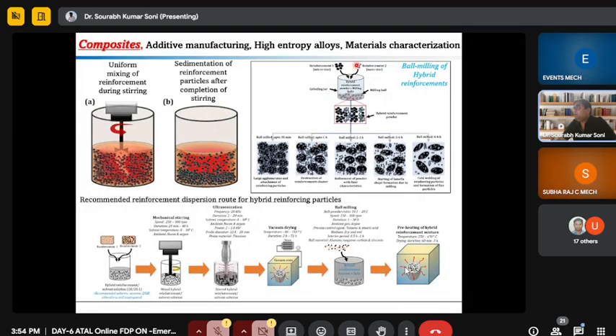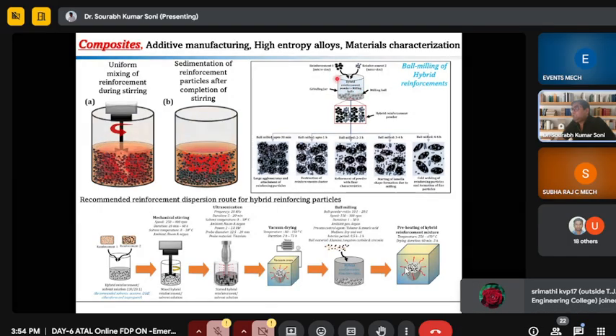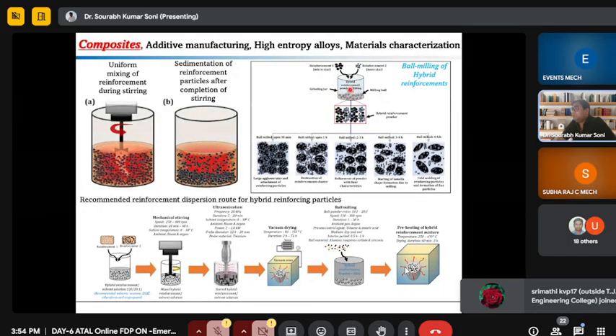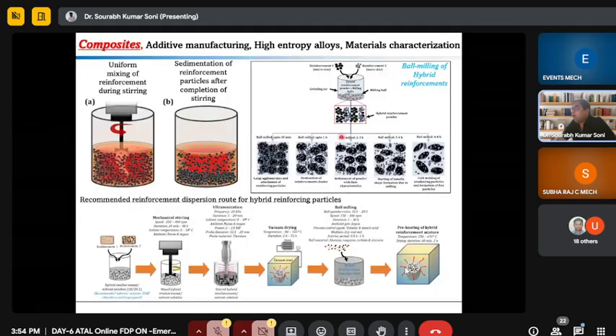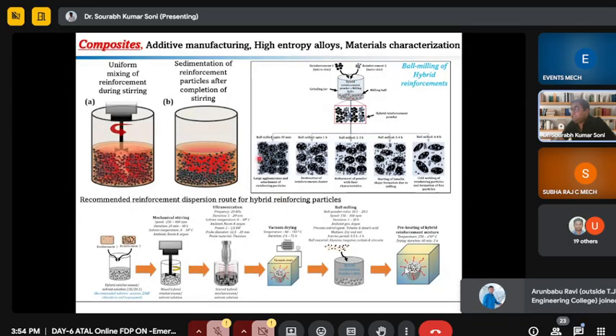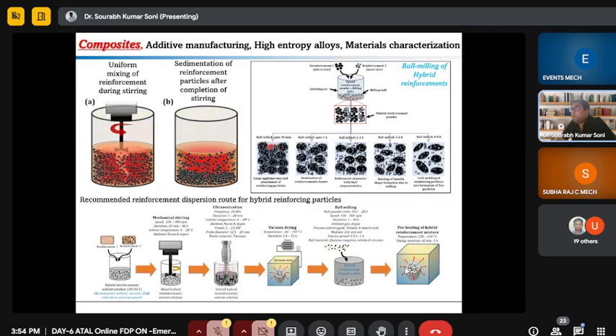And what is the phenomenon going on in ball milling? As you can see here, this is the jar. In this jar, hybrid reinforcement powder is there, and milling balls, obviously. If we ball mill the powder, initially for 30 minutes to 1 hour, what is going on? You see coating of the reinforcement particle in the matrix material, or 1-2 reinforcement particles between them. It totally depends on what kind of reinforcement material you are using.